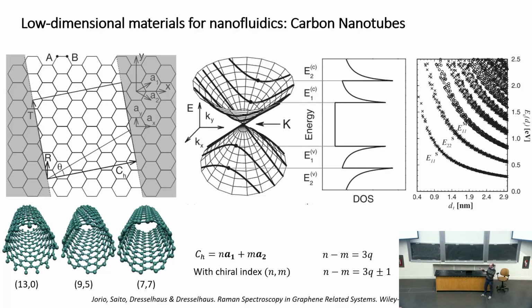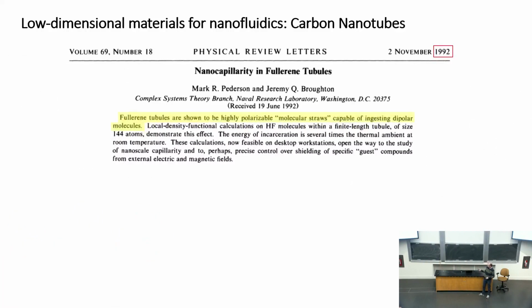But so it's a nice tool, actually. We can go in and select, if you want, like 0.9 nanometer, anything between here. If you're able to resolve it, we can actually do very finely resolved diameter studies in nanofluidics in this space. This has been realized very early on, so 1992, 1 year after the discovery of CNTs, people already dreamt that they would be highly polarizable molecular straws. You could put fluids in and study these.